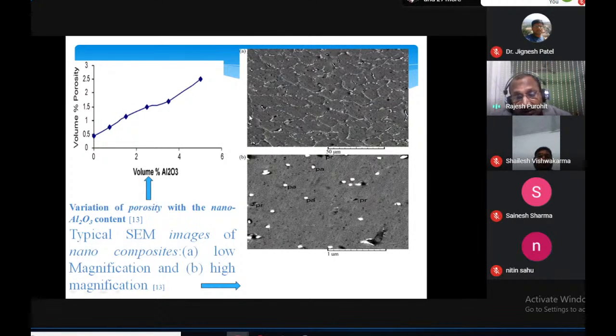On the right side, the SEM micrographs are shown. The upper figure shows a lower magnification, and the bottom one shows the SEM micrograph at higher magnification. We see that the nanoparticles are quite visible in the bottom figure, and they are almost uniformly distributed. Uniform distribution is there.